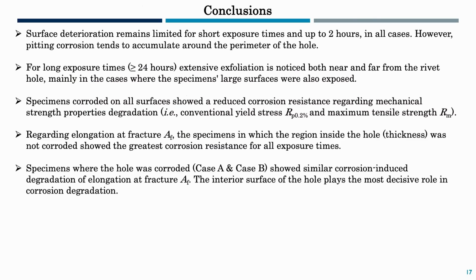So reaching our conclusions, surface deterioration remains limited for short exposure times, up to 2 hours. However, pitting corrosion was gathered around the perimeter of the rivet hole. While for long exposure times, extensive exfoliation was noticed on the large surfaces, both near and far from the rivet hole,